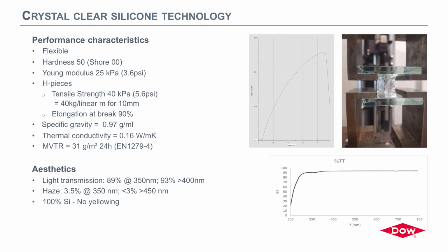Performance-wise, it's a flexible material. Actually, I forgot, I have a sample here. I can show you. It's totally flexible. We achieve a hardness of 50 on the 00 scale. We reach a Young's modulus of 25,000 Pascal. So really the dog bone test piece, the real material property. And in H pieces, our tensile strength is set at 40,000 Pascal.